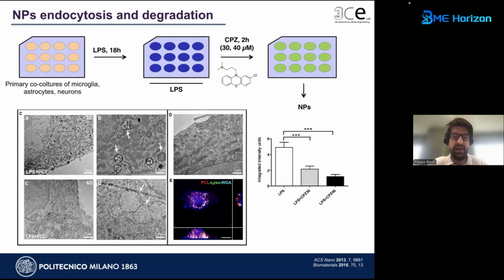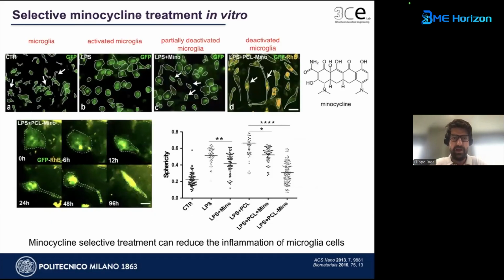These nanoparticles enter, you can see from TEM analysis, within lysosomes, and you can see from the lower part of the picture that after 6 days they are almost degraded by lysosomes. We loaded an anti-inflammatory drug, minocycline, to test the ability of this nanoparticle to decrease inflammation.